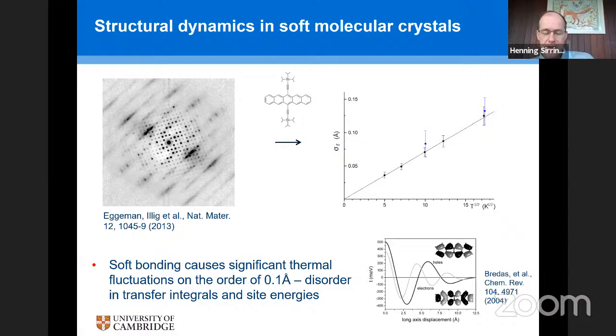And to answer that question, you need to ask how sensitive the transfer integrals are to these relative fluctuations in molecular positions. And you can see that on the bottom right. This is a calculation of the transfer integral of two acene molecules that are shifted against each other along their long molecular axis. If you calculate the transfer integral as you slide the two molecules alongside each other, you can see that these transfer integrals vary very strongly with relative position. The sign changes. There are points where the transfer integrals are 0. There are points where the transfer integral goes through maxima or minima.